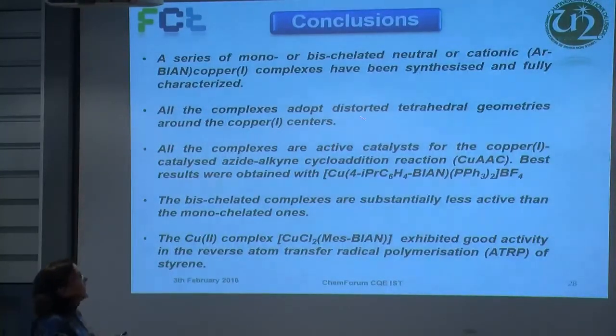All the complexes are active catalysts for the copper-1 catalyzed azide-alkyne cycloaddition reaction, CuAAC. Best results were obtained for the bis triphenylphosphine complex with the 4-isopropyl in the arene. The bischelated complexes are substantially less active than the monochelated ones, and the copper-2 complex with the mesityl 2,4,6-trimethyl exhibited good activity in the reverse atom transfer radical polymerization of styrene.